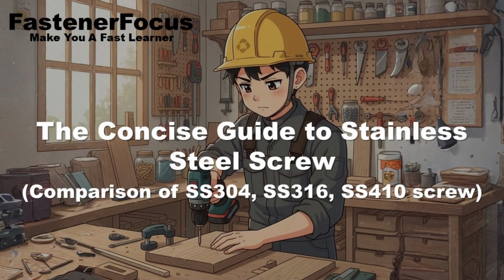Let's start with chromium, the primary corrosion fighter and the defining element of stainless steel. Okay, so grade 304 contains 18 to 20% chromium. Grade 316 is slightly lower, with 16 to 18% chromium. The martensitic grade 410 contains the lowest amount, only between 11.5 and 13.5% chromium. The lower chromium in 410 immediately signals its lower baseline corrosion resistance compared to the other two.